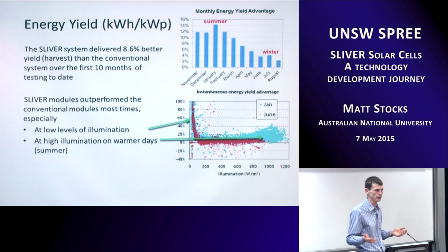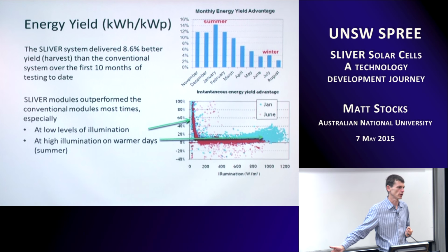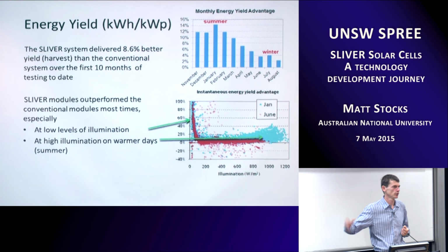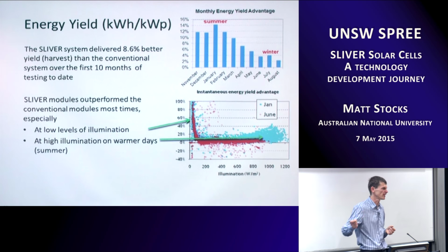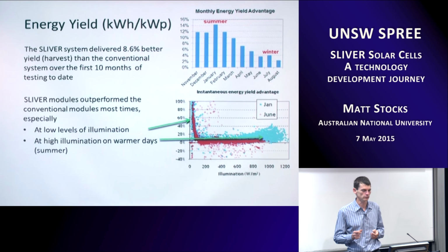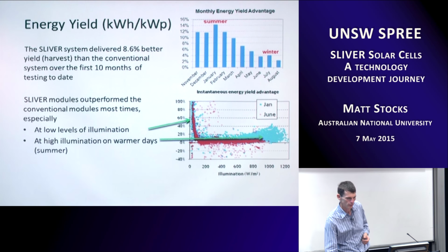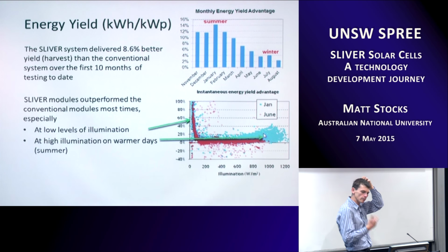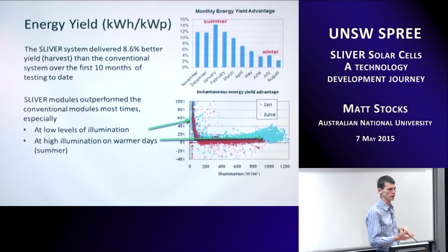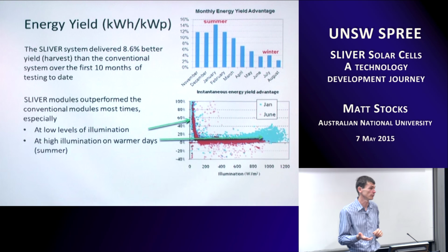We have got better energy yield than the standard one, and that's all about the high voltage. Okay, because we've got a high open circuit voltage, when things get hot, you lose less voltage than a lower voltage competitor will. And that's really where most of our gain was, that we were getting much better voltage out of our modules on the very hot, bright, sunny day, which is really where you want your performance to be in terms of getting the most energy out of your system.